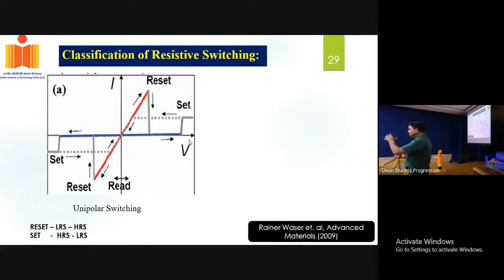If there is a rupturing of the filament of this oxygen defect, you can call it a high resistance state. It all depends upon how you go from the low resistance state to the high resistance state, or the high resistance state to the low resistance state. If you go from low resistance state to high resistance state, you call it a reset process. If you go from high resistance state to low resistance state, you call it a set process.